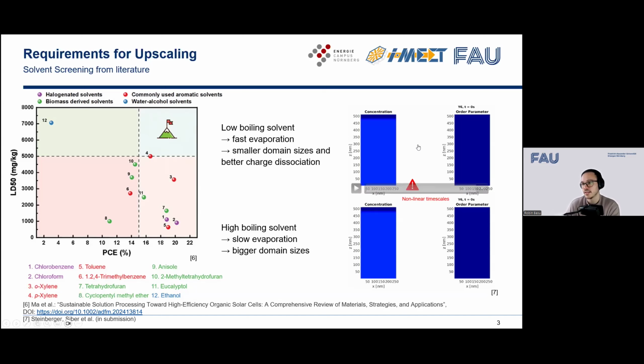And so why is the solvent important? The solvent directly affects the morphology of our active layers in OPV. If we have a low boiling solvent, we usually see fast evaporation, and that usually gives us smaller domain sizes, and that leads to a better charge dissociation. I have a small simulation by Max Steinberger and Maxim Sieber that really shows you quite fine domains here for the fast evaporating solvent. And for the high boiling solvent, you can tell that the domains are significantly bigger, and with that, we have worse charge dissociation. So ideally, we'll have a lower boiling solvent that gives us the desired morphology.